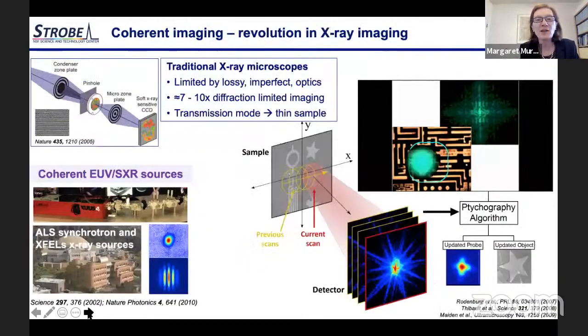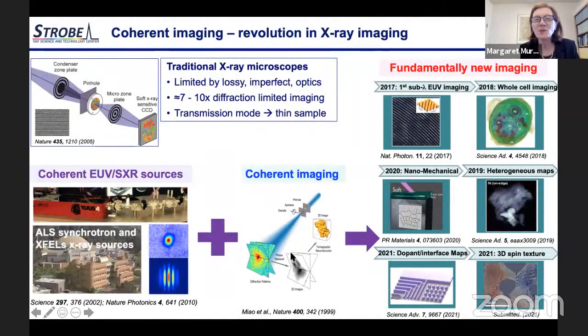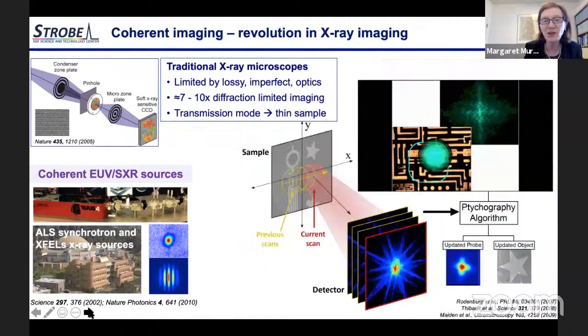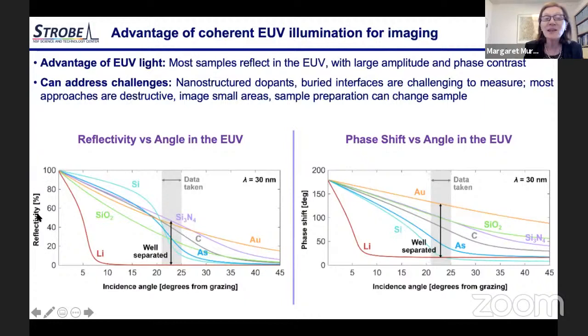so maybe I should go back one slide. Usually coherent imaging is implemented in transmission mode in the soft X-ray region, because soft X-rays penetrate structures very nicely, but they don't reflect off structures. High harmonics are very bright in the extreme UV region. And the wonderful thing about that is that in the extreme UV region, materials are very reflective. So what's plotted here is the reflectivity from different materials: lithium, silicon dioxide, silicon, silicon nitride, arsenic, carbon, gold, at a wavelength of 30 nanometers as a function of angle.